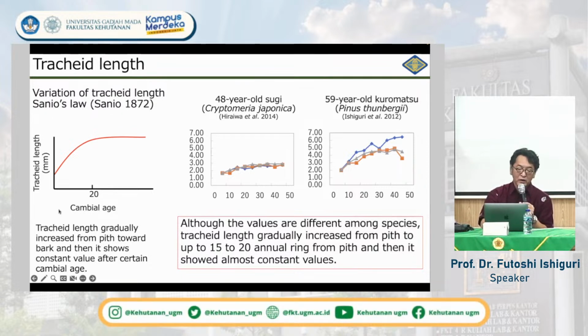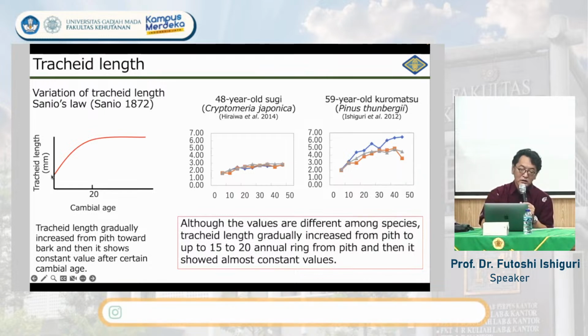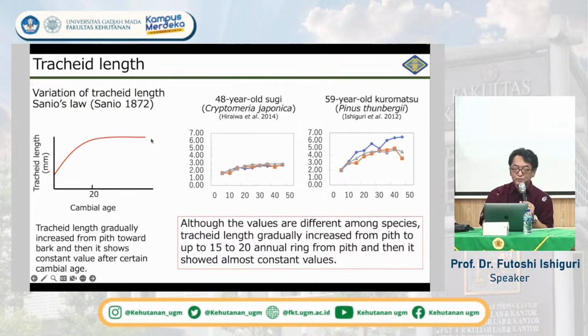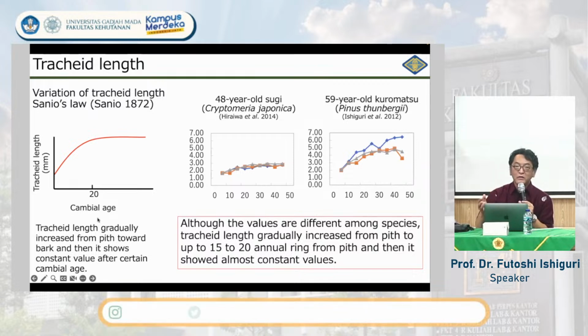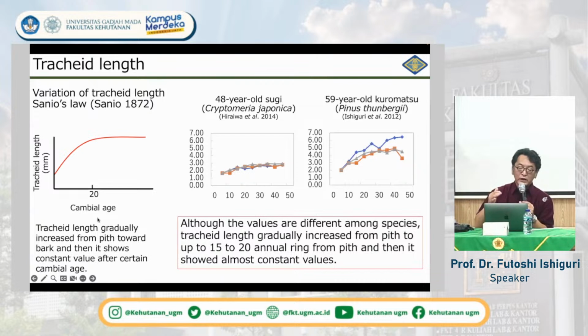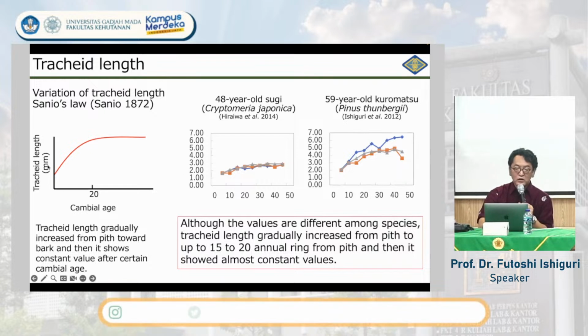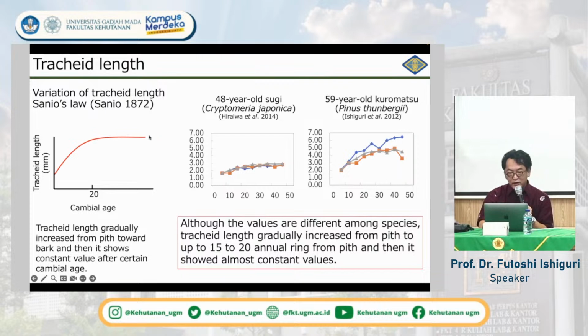It describes the tracheid length as shortest at the pith position, and it gradually increases, and then becomes stable. That is around the 20th annual ring. And here the annual ring is also not so popular, but in temperate zones the growth season occurs just one time in a year, so we find growth rings. So that's why we can determine this by using the growth rings. Anyway, it is shortest at first, then increases and becomes stable.